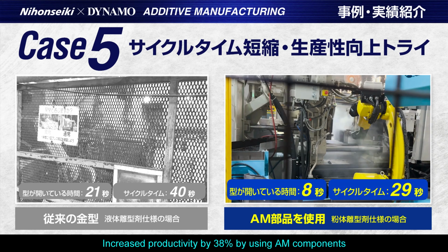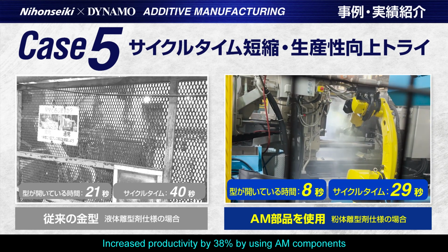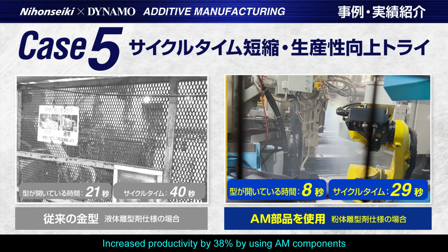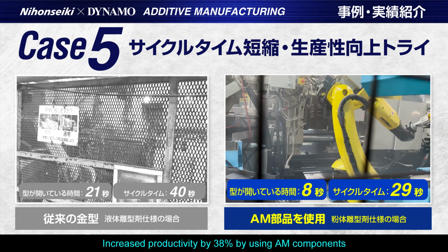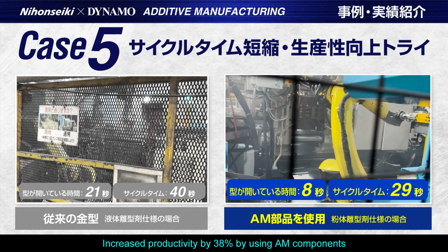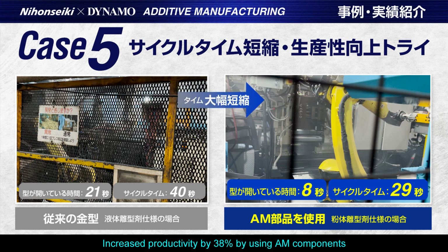By the way, in this case, the mold release agent is applied by pressing the powder release agent from the sprue just before pouring molten aluminum. This is the only release agent for the mold to release the product, and it also leads to environmental improvement because it requires the minimum necessary usage. In this case, productivity has increased by 38%. This is quite innovative.